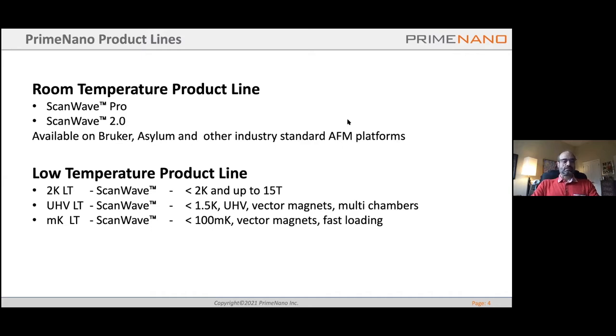The low temperature product line has three products under it. 2 Kelvin low temperature, which is sub 2 Kelvin and up to 15 Teslas of magnetic field. An ultra high vacuum low temperature ScanWave. It's going to go below 1.5 Kelvin and ultra high vacuum. It's in high magnetic fields. And this can be connected to a chamber for deposition and transfer in vacuum. And then we have the millikelvin product, which can go to below 100 millikelvin with high magnetic field and fast loading.